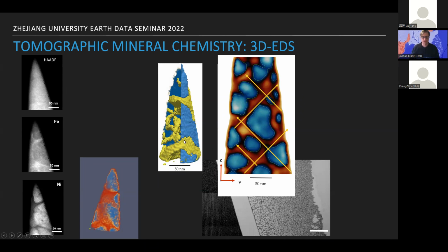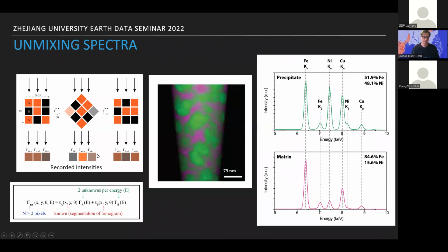And this is even after doing principal component analysis on the spectra, which we used to recover these iron and nickel maps very well and to align the volumes. But when we quantified them, the quantification was not quite right. So what we did instead, with my colleague Sean Collins, who had developed a technique, is move from the unmixed signal, which we work with in the reconstructed volume, and back project to the original mixed signals from each slice, and that transforms the original signals into a series of thickness maps. In this back projection and recombination, we're able to unmix how much each pixel is contributing to each of the phases.